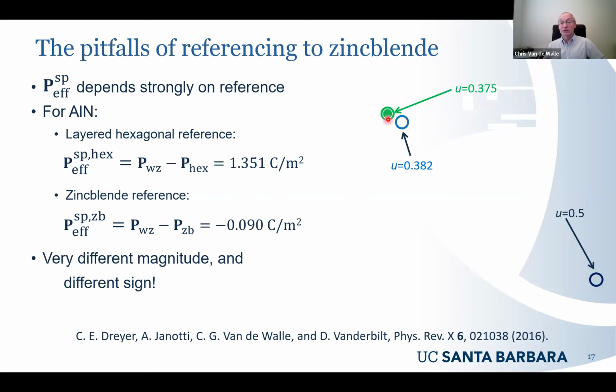So if we choose zinc blende as the reference structure, we're going to get a different sign of the spontaneous polarization. And we're going to get a different magnitude, because zinc blende and Wurtzite in magnitude don't differ that much, less than the difference with the layered hexagonal structure. So you're going to get a much smaller magnitude. Instead of 1.3 something, you get minus 0.09, like 2 orders of magnitude smaller. Okay, so this is why there has been understandably confusion, because in the field of nitrides, people have implicitly used the zinc blende reference. And if you use those values, you obtain very different magnitudes and signs of polarization differences.